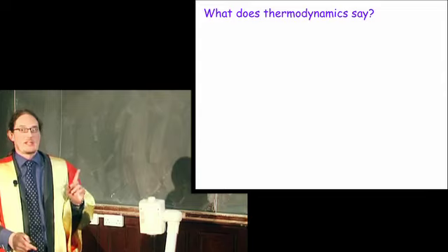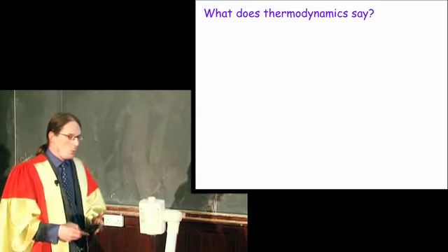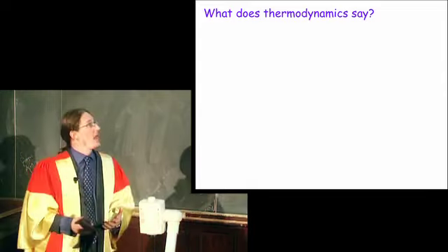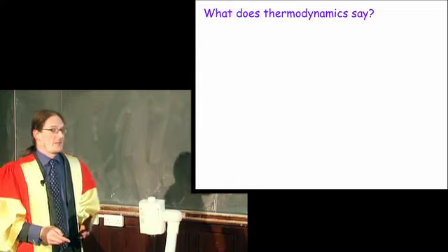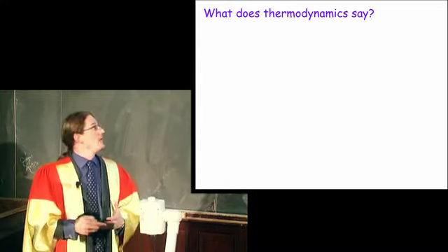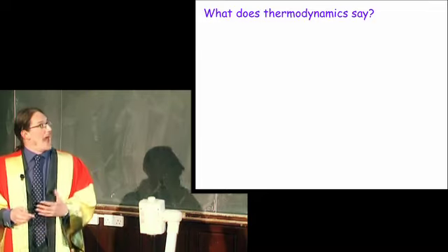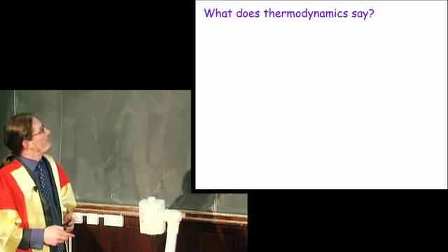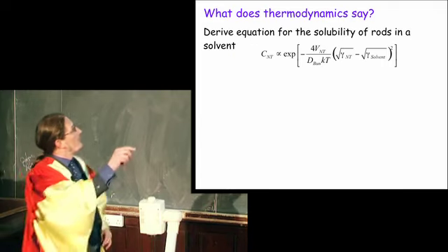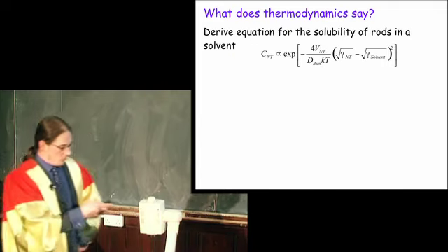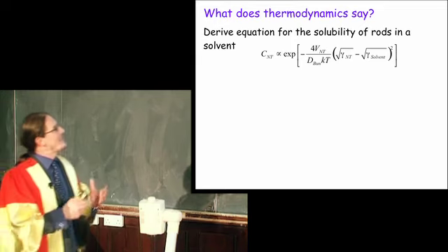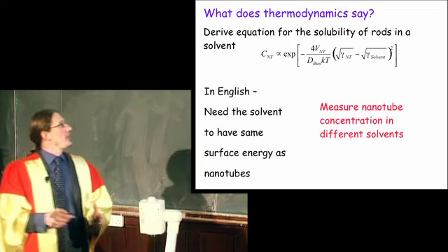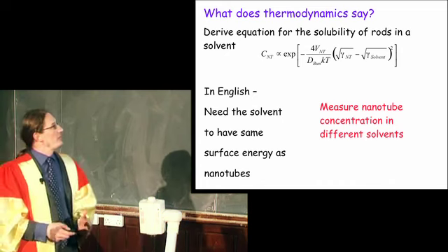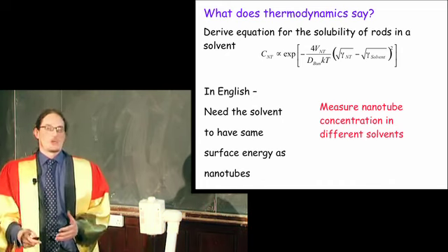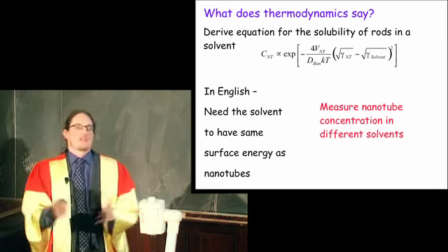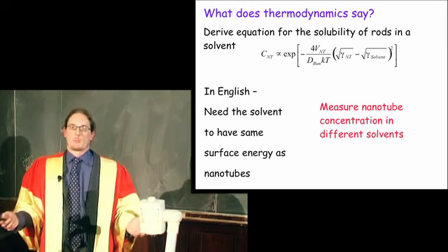And this is the only really technical slide that I'll have. So we used a branch of physics or chemistry, depending on your point of view, called thermodynamics, and we were able to theoretically calculate how much nanotubes we could disperse in solvents. So the concentration given by this equation, I don't want to bore you with the details, but to translate it into English, what it means is that if you want to disperse nanotubes in the solvent, the solvent and the nanotube must have the same surface energy. And surface energy is just a property of materials. You can look it up in a book.